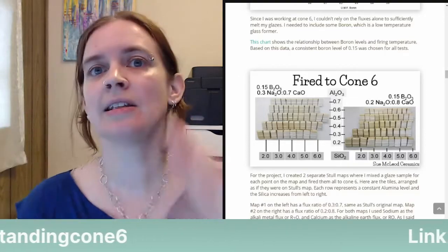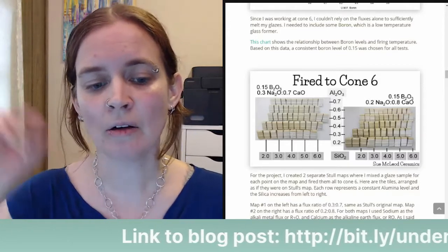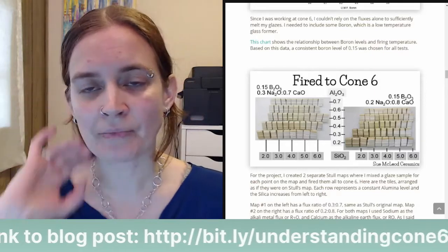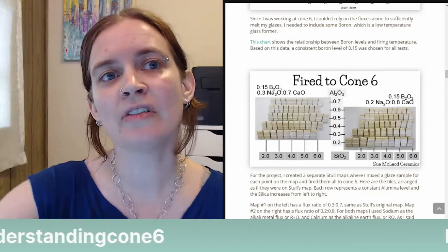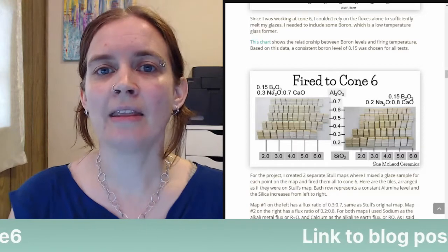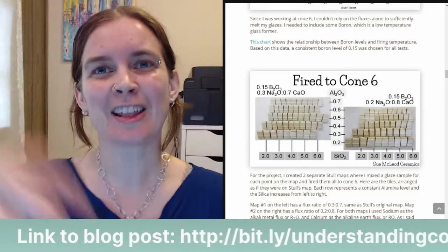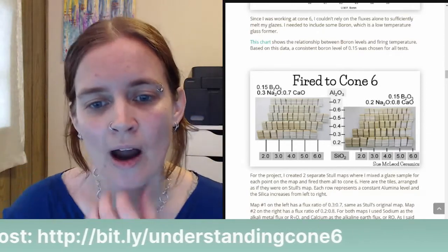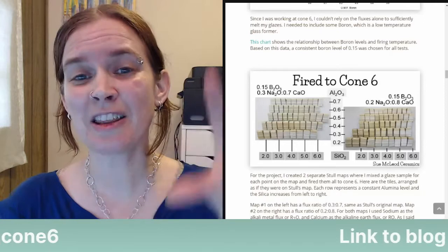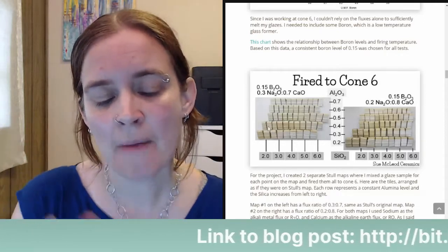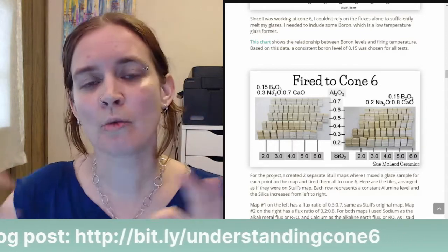And so as long as your glaze is homogenized, you are removing a little bit of glaze with each dip of a test tile. Hopefully I'm answering your question. Let me know. So you're removing a little bit of glaze, but as long as the glaze is completely homogenized, you're removing everything in proportion to each other. And the larger your test sample is, the less material you're removing from it. So it's not perfect because I'm adding silica based on the original recipe that I hadn't dipped a test tile in, but the results are generally going to show you what adding silica does.